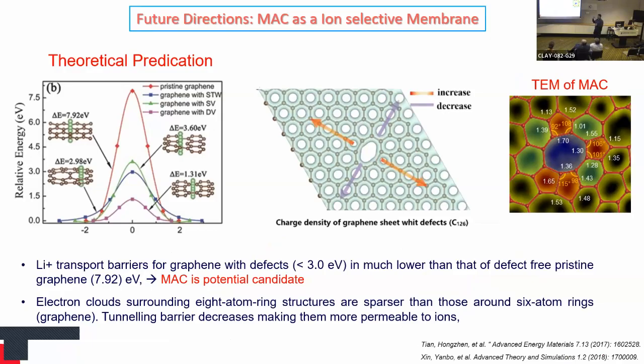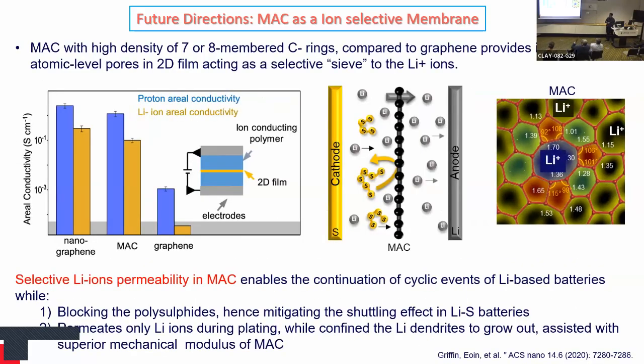So how can we use it as selective membranes? The theoretical papers suggest that graphene has a very high transport barrier for ions, but once we have defects like these 8-member rings, it enhances the permeability for different ions. For example, for lithium, the barrier lowers to about 1.3. So that's why we can use this material as a membrane or sieve. Actually, one of our collaborating groups did an experiment, not by us, for a proton membrane as well as a lithium ion membrane. They tested and saw that it is quite high compared to graphene, for both proton and lithium, but this is just for one type of material. Of course, if we change the material, we can change the permeability.